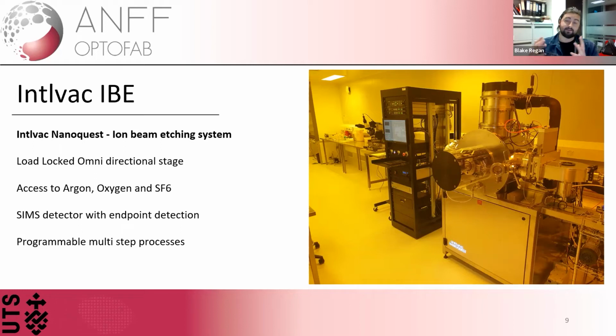We do have access to argon, which is the predominant gas. If you go through anywhere in the literature on ion beam etching, you're going to track down argon-based etching, especially for silicon structures. But we also have access to oxygen and SF6. The primary reason is there are occasions where you'll want to have good or better mask selectivity between your different materials, if you're attempting to generate structures. And occasionally, depending on your substrate, you do need to have a chemical selective part of the etching mechanism, which will allow the masks to have different levels of effectiveness when generating nanostructures.